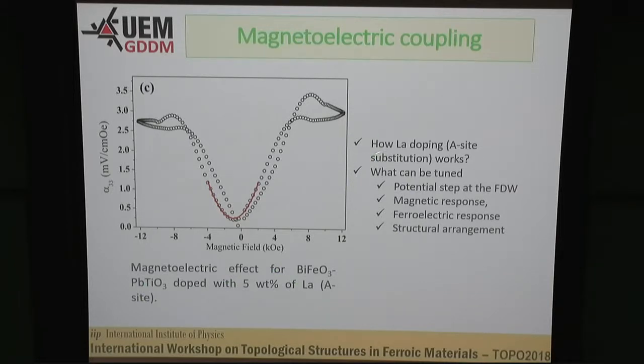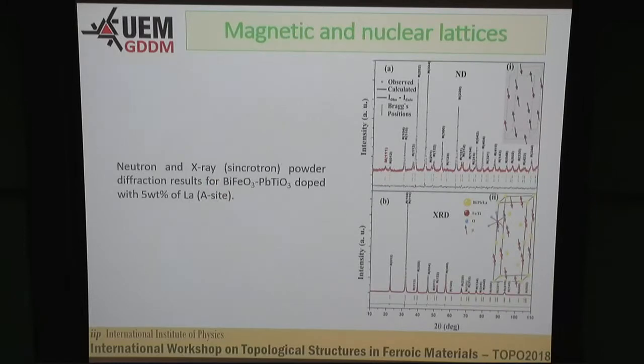But here we have a question: how does lanthanum doping in an A-site substitution work? What can be tuned in this case? Potential step at the ferroelectric domain walls, magnetic response, ferroelectric response, structural arrangement. To see this better, we also did high resolution synchrotron X-ray diffraction and high resolution neutron diffraction to construct the magnetic lattice of this sample, to propose the magnetic model for the magnetic ordering, and also to see the complete structural arrangement of these materials.